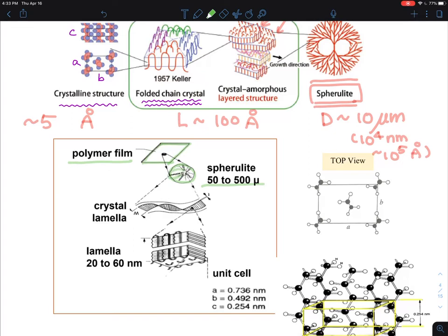Within this big scale, they consist of the lamella crystals, and this is what sometimes they call the lamella ribbon, because they are twisted in a way to make up the effect. We fill out the surfaces, spaces in three dimensions. Within the lamella structures, what are the thicknesses of this lamella that is in the range of 10 nanometers to multiples of 10 nanometers?